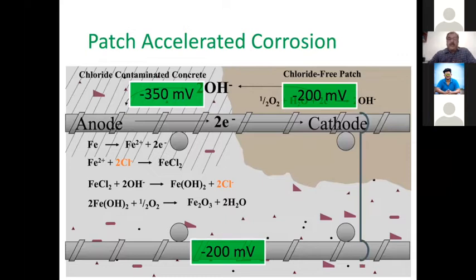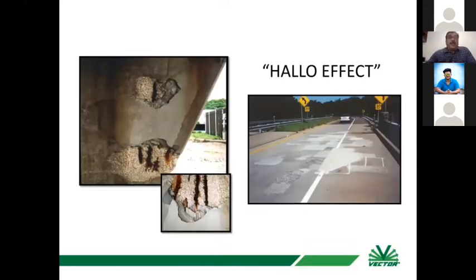And in this case, by doing the patch repair, what we had done is induce corrosion in the adjoining good concrete, or good concrete which is having steel with contamination will get corroded. This is called halo effect or incipient anode formation. You can see there are two patches for one patch repair, and the road on the right side is repaired n number of times because of halo effect. We don't want this. This patch stays for only a few years and then you need another repair.